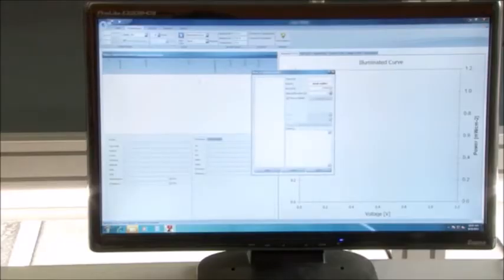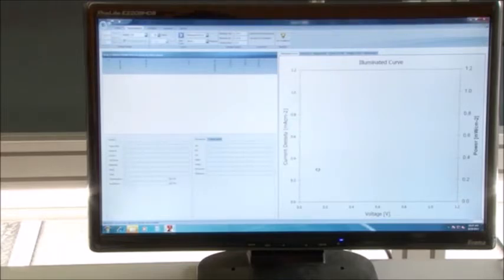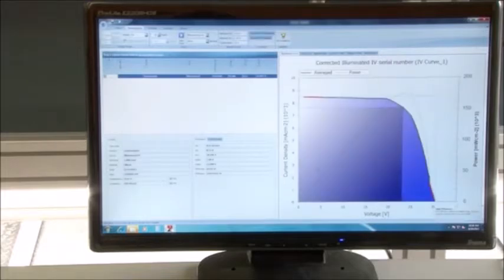A software program controls the JV measurement. The voltage over the panel is varied while the current is measured. On the screen, the resulting JV curve and power density is plotted from 0 volts up to the open circuit voltage. As the setup measures the total current of the panel, the active area of the panel is an input parameter for the software. Using the given active area, the software calculates the current density of the panel. In this example, the maximum power density is 17.4 milliwatts per square centimeters, which corresponds to a panel conversion efficiency of 17.4%.